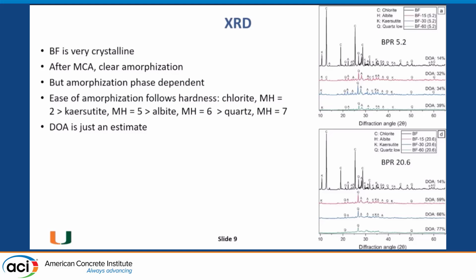However, there is clearly some heterogeneity here, meaning that some peaks vanish very quickly, whereas other peaks persist. And what we found is, qualitatively speaking, the ease of amorphization, that is the ease at which these peaks vanish, depends very strongly on the hardness of these particles. So again, this is just an estimate, but in this system we find that as the Mohs hardness goes from 2 to 7, the ease of amorphization, the persistence of those peaks, changes markedly. So again, these are just estimates. I realize that these are not the most perfect numbers, but that's okay for now.